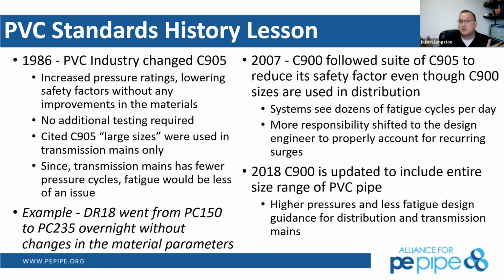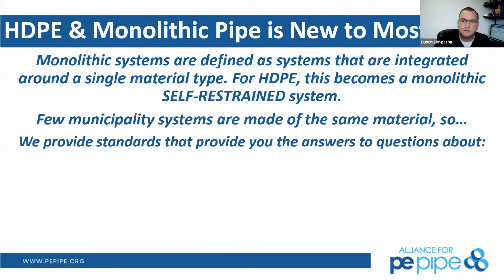So with that change, though, for the PVC industry, it put all of that design criteria for cyclic fatigue and fatigue failure onto the engineers. And it said, hey, if you're going to use PVC, we're going to rate it at this higher static pressure rating. But if you have flow velocities, X amount, this many cycles, this much fatigue, you need to be designing it for those cycles. And so overnight, they were able, again, to increase the pressure classes to better compete with ductile iron's 350 PSI pressure rating. But they kind of did it with a sleight of hand, putting all of the onus of design onto the engineers and taking it away from the standard.